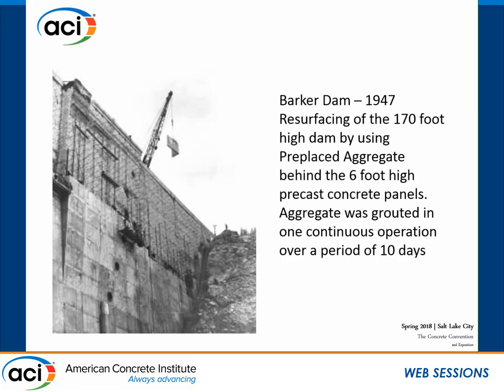Here's another one near where I live — the Barker Dam in Nederland, Colorado. This dam was strengthened and resurfaced in 1947. They did this in the wintertime when the water in the dam was very low, built forms using precast concrete, filled the forms with aggregate, and got it all built up before grouting any of it. Then they filled the dam with water for two reasons: to preload it and to cool the concrete, since the hydrating concrete gives off tremendous heat. They grouted this in one operation, bottom to top, over 10 days.